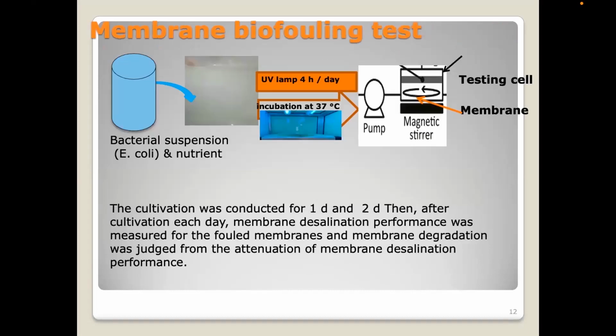Membrane biofouling test. We prepared our membrane and submerged it in bacterial suspension of E. coli in nutrient broth. Every day, after bacterial growth, we expose our membrane to an ultraviolet lamp for 4 hours per day. After these 4 hours, it is incubated for the next day at 37 degrees.